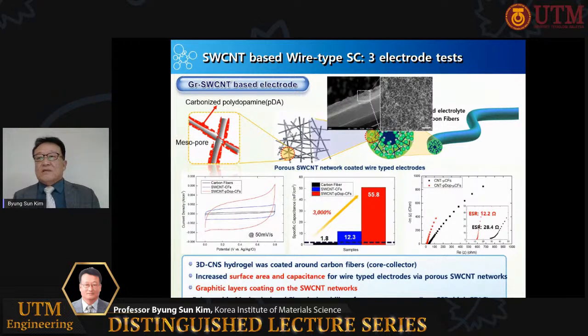Increased surface area and capacitance for wire-type electrodes via porous SWCNT networks are obtained. Graphitic layer coating on the single-wall CNT networks is established, which enhanced the mechanical and electrical stability of porous structures, which possesses low equivalent series resistance and high electrical double layer capacitance.